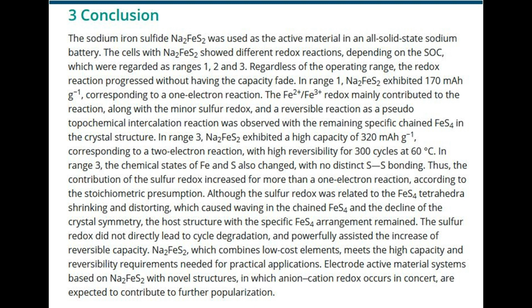In range 3, Na2FeS2 exhibited a high capacity of 320 mAh g-1, corresponding to a 2-electron reaction, with high reversibility for 300 cycles at 60 degrees C. In range 3, the chemical states of Fe and S also changed, with no distinct S-S bonding. Thus, the contribution of the sulfur redox increased for more than a 1-electron reaction, according to the stoichiometric presumption.